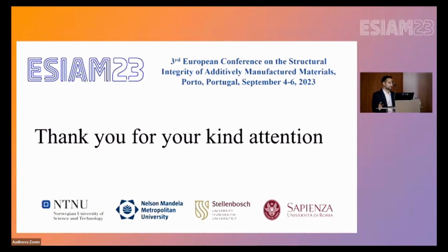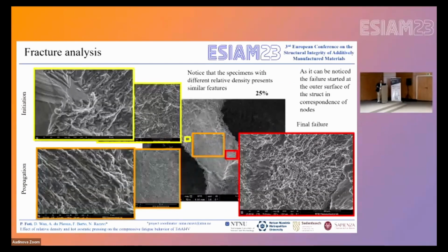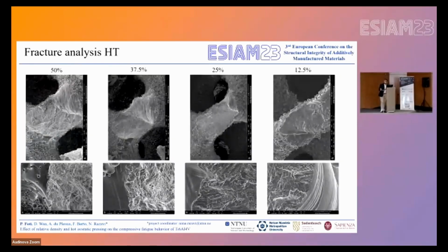Thank you for your nice presentation. One question: were your specimens treated in a vacuum environment or in a protected atmosphere environment? Because I suspect that the great role played by the surface in dictating the effective behavior could be attributed to the presence of an alpha case on the surface produced by oxygen contamination, which is very brittle and can initiate the fatigue damage. So I suggest you look at the surface microstructure. You should take a metallographic cross section.